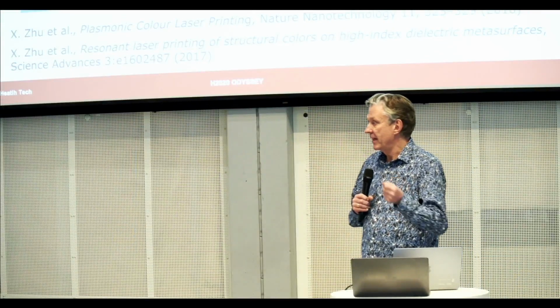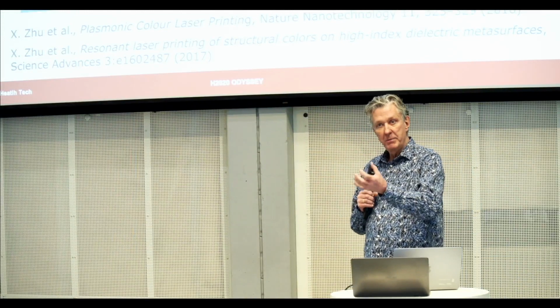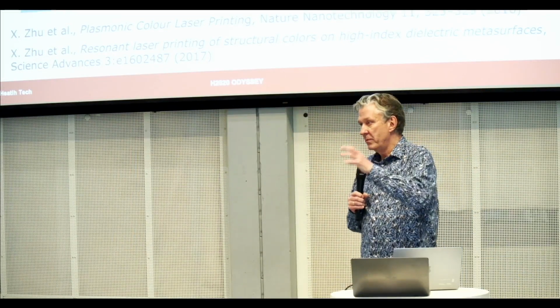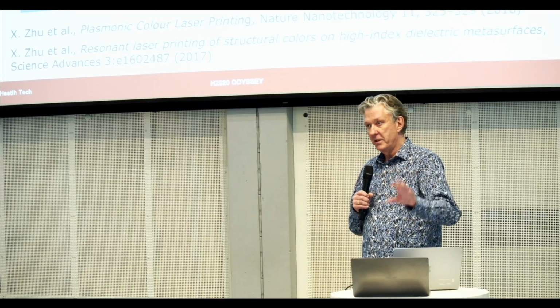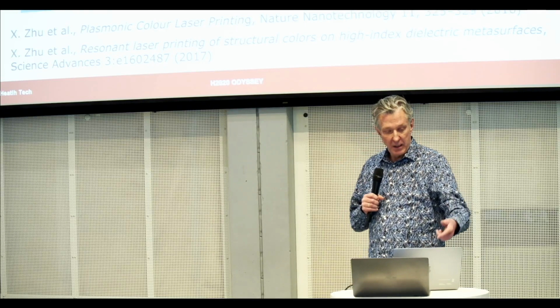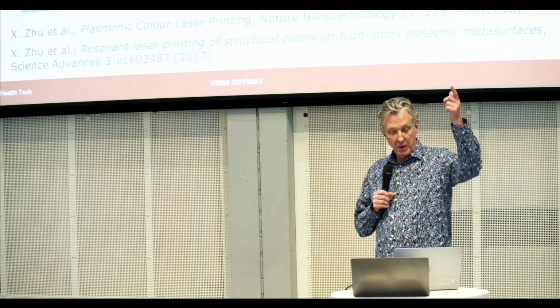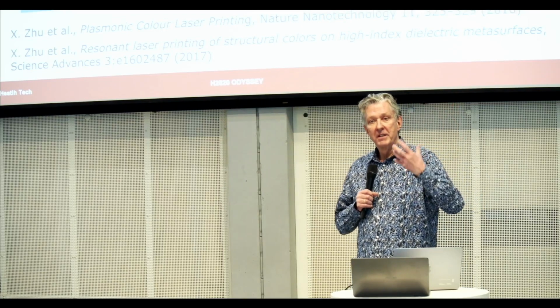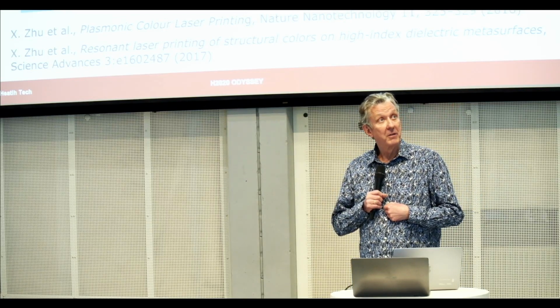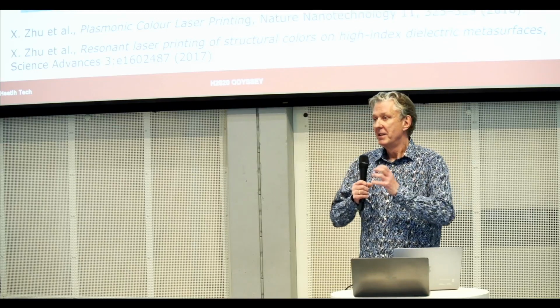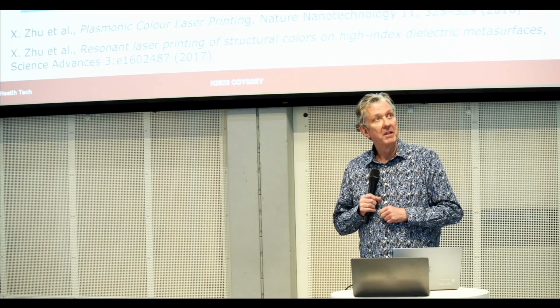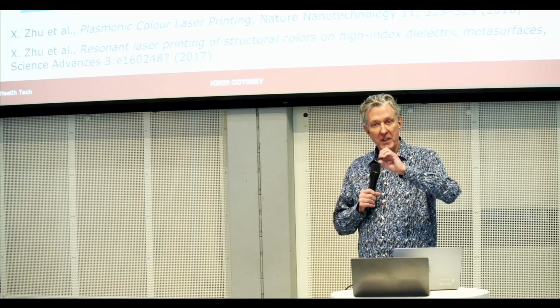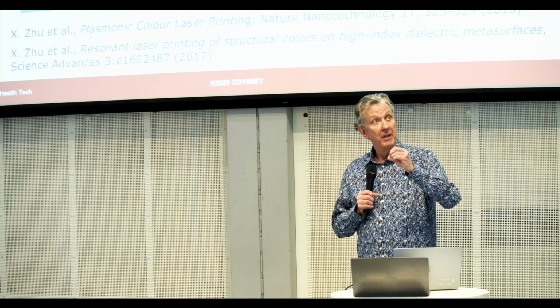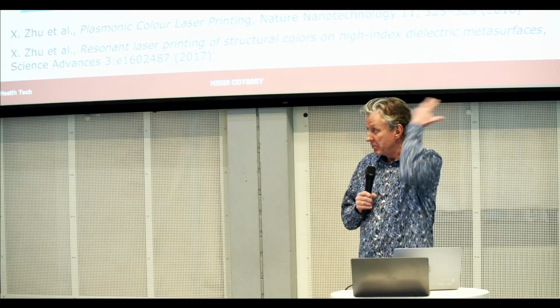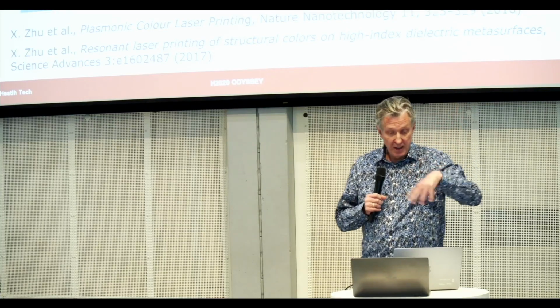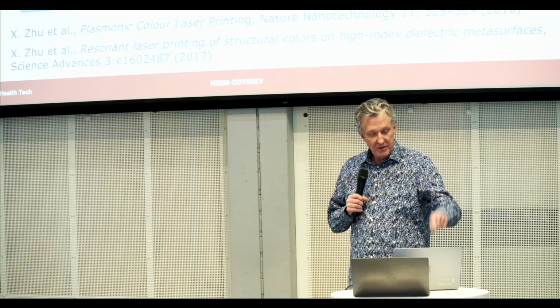and then depending on how much energy we deliver in this pulse, we change locally those nanostructures from the original disk to something else. As you can see as we go down, we gradually increase the energy in this laser pulse. So we can start by just using melting or reflowing, so you're making the corner soft. You can de-wet the surface, so you get a small ball of the material sitting on top. And you can even ablate, so remove all the material and start machining also underneath. And this gives different colors.